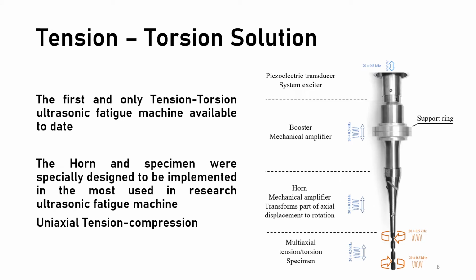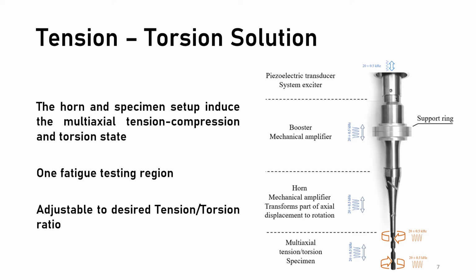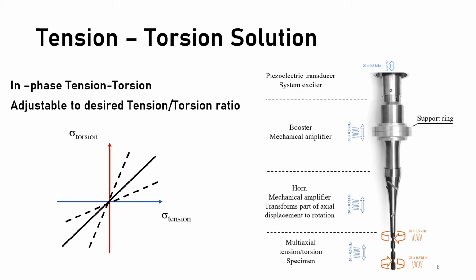So here we present our solution towards tension and torsion in ultrasonic fatigue methods. To our knowledge, it is the only multi-axial tension torsion ultrasonic fatigue machine available to date. We use as its base the uniaxial tension compression ultrasonic fatigue machine, the most used in research. We changed the horn and the specimen in order to include the torsion in addition to the tension compression already excited. We have only one fatigue testing region in the specimen, and we can also adjust to a desired tension and torsion ratio. The tension and torsion in this machine are in phase, and we can have a lower shear to tension, equal torsion to tension, and even a higher torsion to tension amplitude.